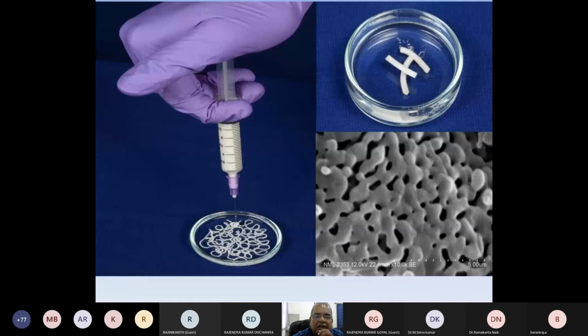We took our hydroxyapatite, simply made it a paste with the help of a buffer, put it in a normal 24-gauge syringe, and directly injected this paste into water. You look here, we are injecting into the water. I have the video, but I am not running it here. There was some bubble formation because air was entrapped in those extruded structures of calcium hydroxyapatite. And after that, they were stable. There was no degradation, there was no anti-washout effect.